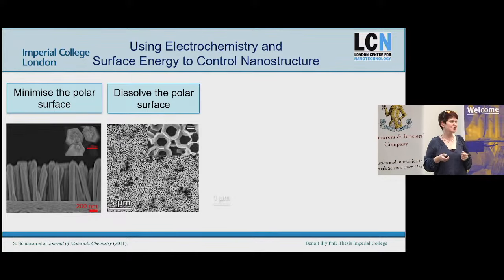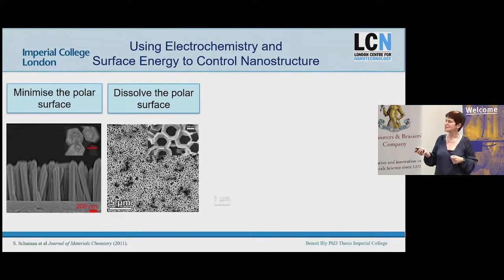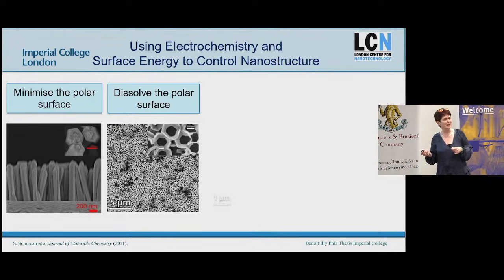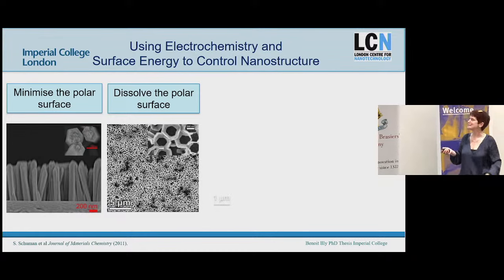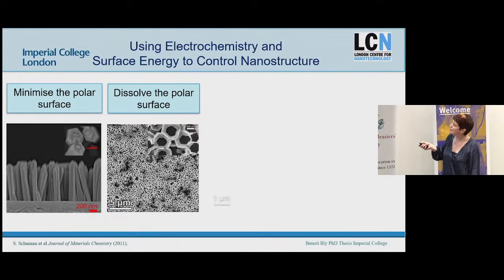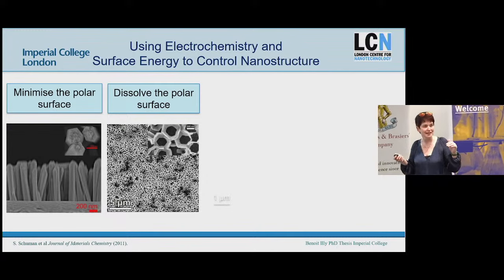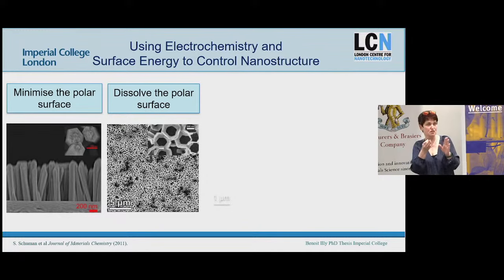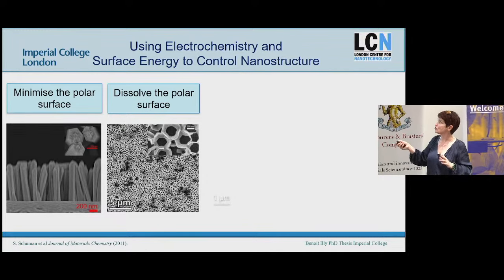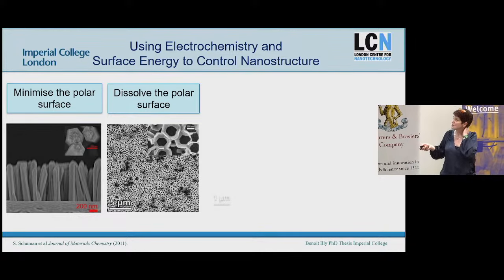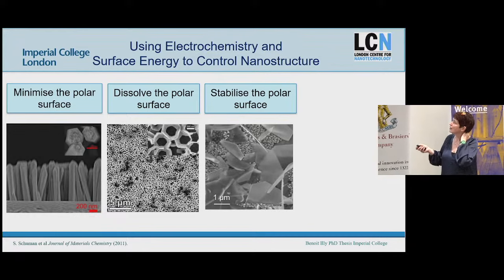You can actually then just dissolve the polar surface. Who knew that was hard to say? If you let this redissolve, if you change the pH so it goes back to dissolving, it turns out the sides here, which we already did know were more stable than the surface, actually, if you get the conditions just right, it dissolves just straight back down the middle and gives you these beautiful tubes, which are really interesting for things like catalysis.